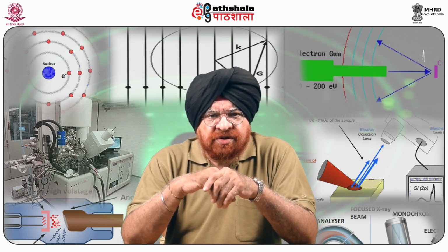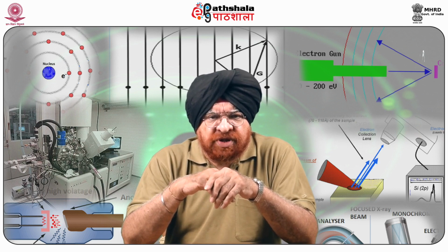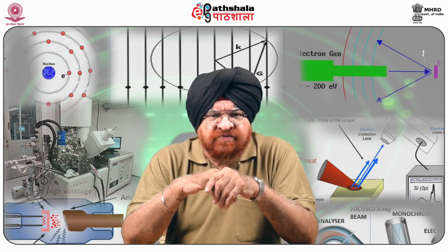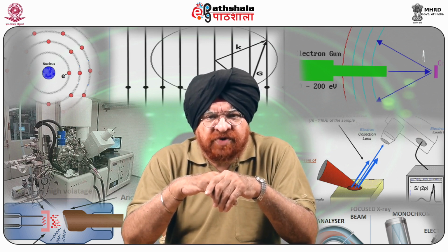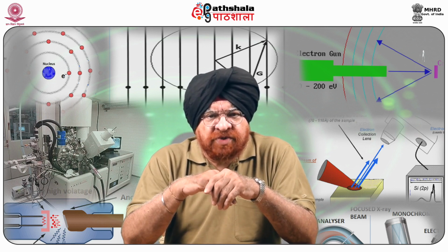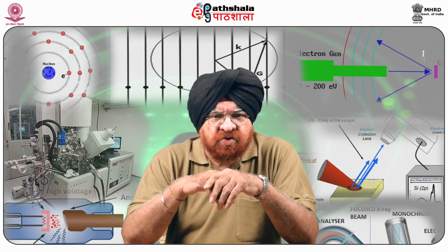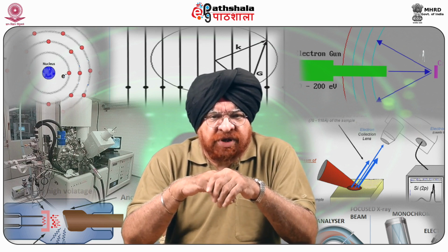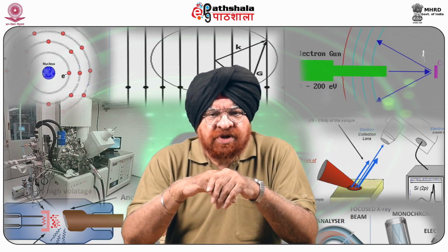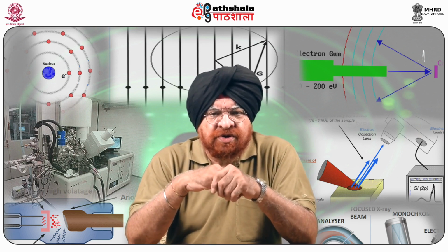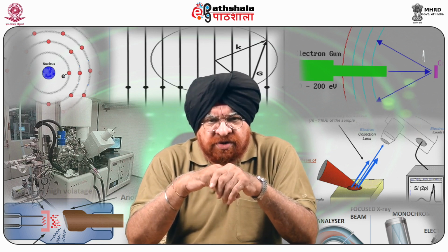By interaction with the free electrons from the cathode, the argon is ionized, resulting in the formation of plasma, which is the fourth fundamental state of matter. The plasma formed is extracted through a series of at least two highly charged grids and finally becomes an ion beam which moves at a very high speed. The figure of the duoplasmatron is shown in the slide.